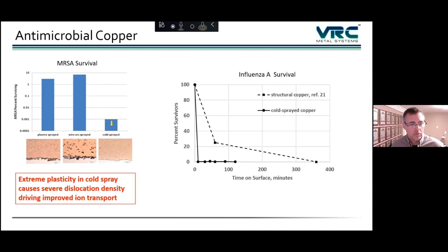comparison to the others. On the right, you actually see influenza A virus. Similar thing, you can see a dramatic reduction in the cold sprayed copper over just wrought structural copper. And this has to do with the severe plasticity that we put into the material causing dislocations. So you get a high dislocation density, and that actually enables the ion transport within the material, which is what gets you your killing properties of these viruses and bacteria. So cold sprayed copper, even better than regular copper, which is far better than most other surfaces.